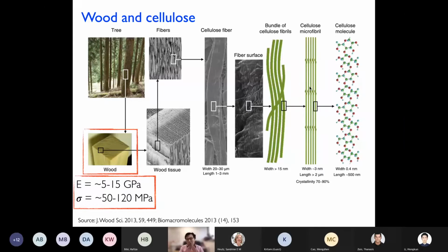If you zoom into wood further, you actually get down to the cellulose fiber scale. So this is actually at the center here. So this will be where you would start making your textile fibers. For example, you would dissolve this cellulose fiber, which you can then use to make textile fibers, or use it as it is. You can then create paper out of it, or paper cardboard out of it, or boxes out of it. And the length scale here is about 20 to 30 micrometers.